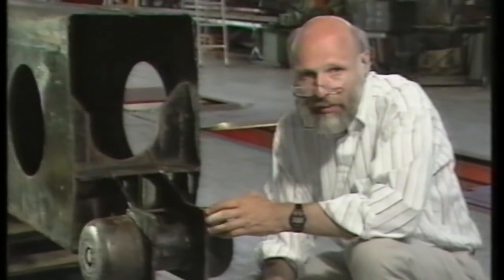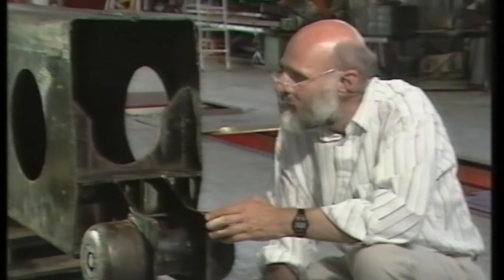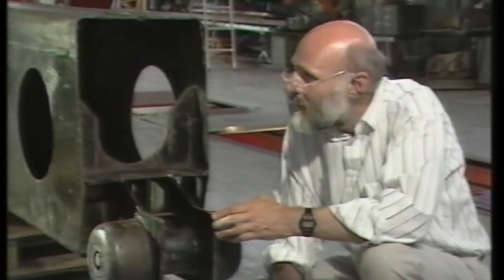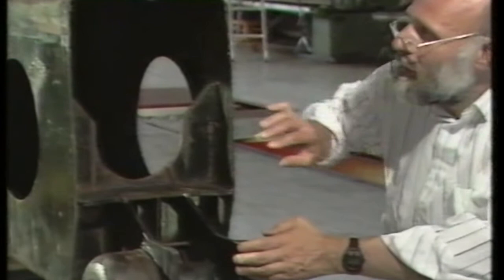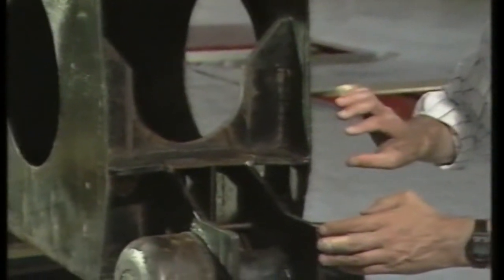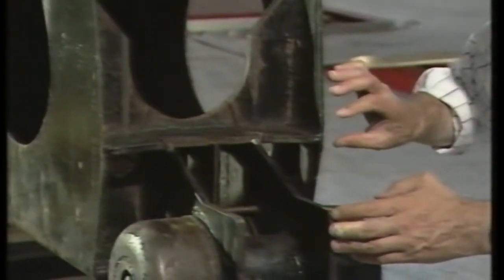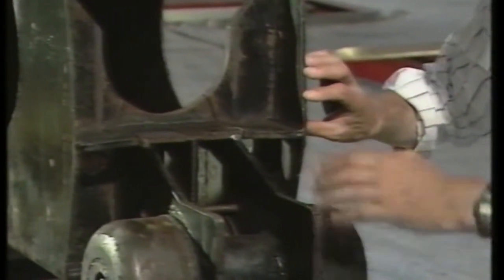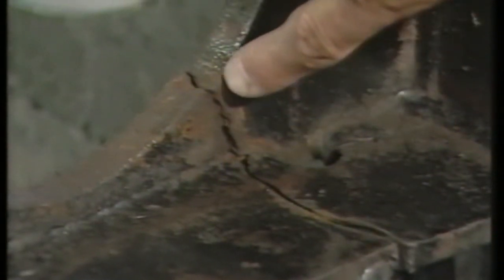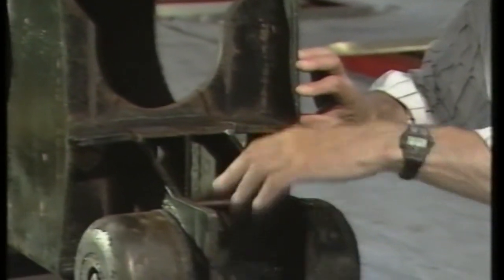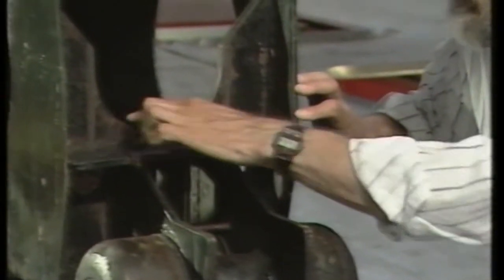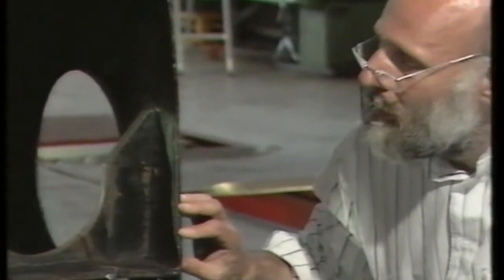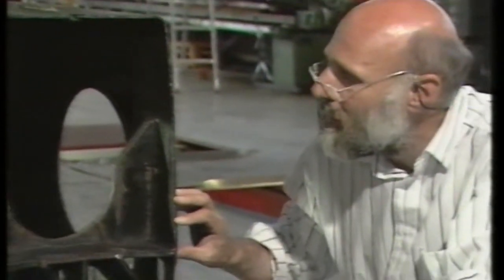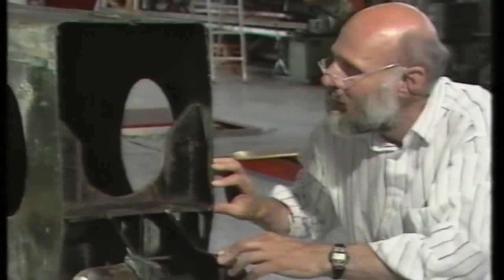We have not only deformations from the accident, but also endurance failure, which is very serious on this crane. This is the backside of the beam, which goes in the next part and has very large cracks. The attachment for the hydraulic cylinder is here, and also for the backing roller. It's completely cracked on both sides. If the crane had not crashed on account of the boat, it would have definitely crashed after a short period of time anyway. One can only establish that these cracks are a construction fault.